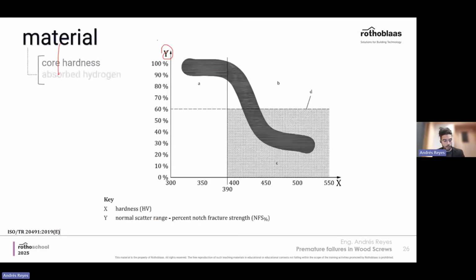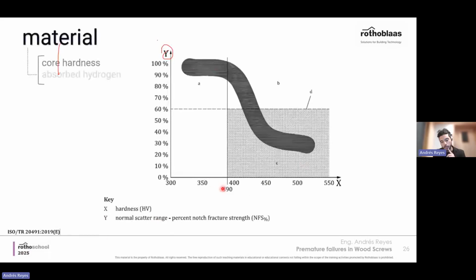Once we are above the 390 threshold, you see here a decay in the performance, in the tensile capacity in this case, of the screw. So you see here a very strong change in the behavior of the fastener, and that means the core hardness tells us how susceptible the fastener is to the presence of hydrogen.